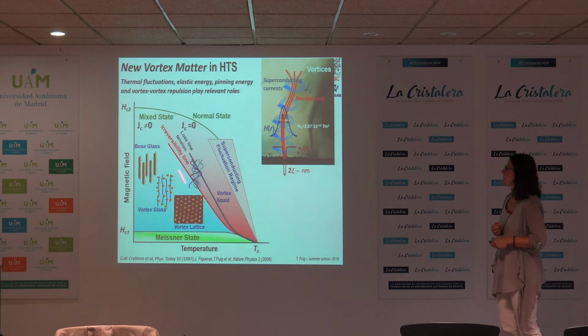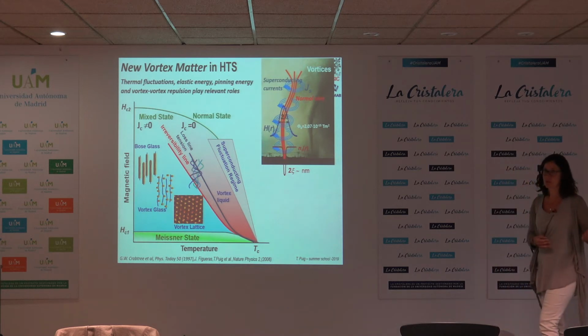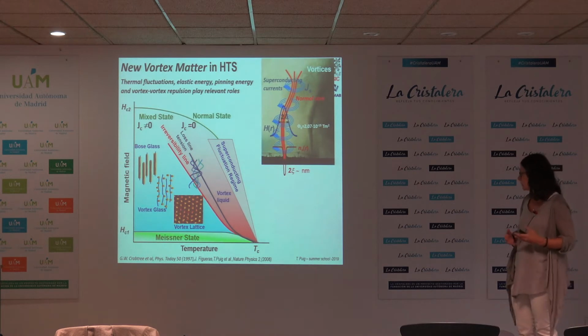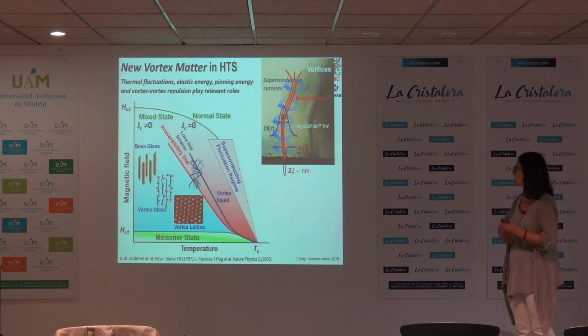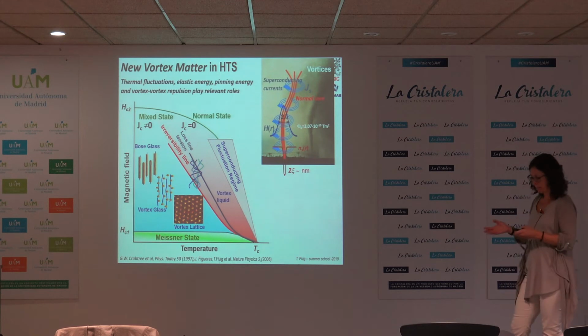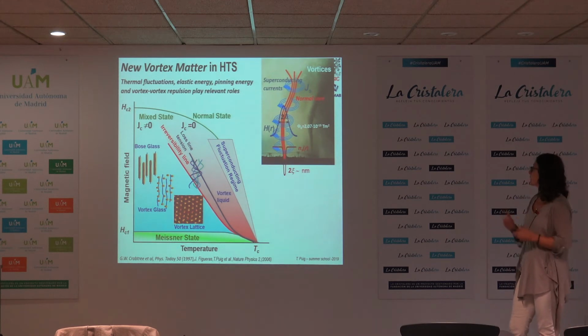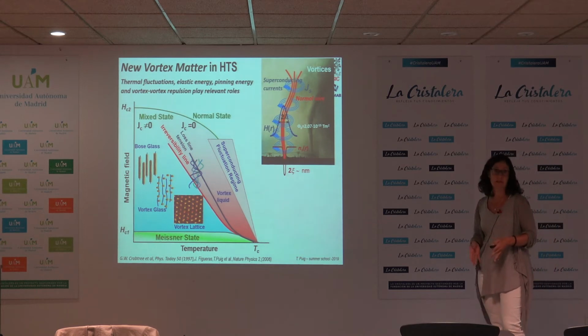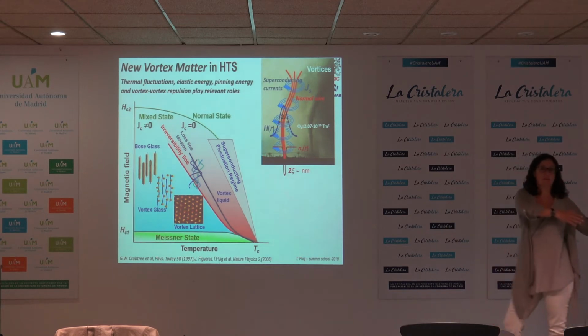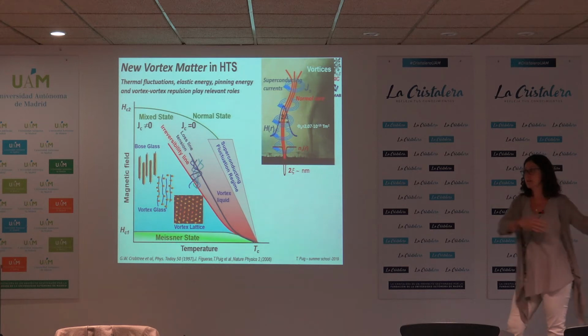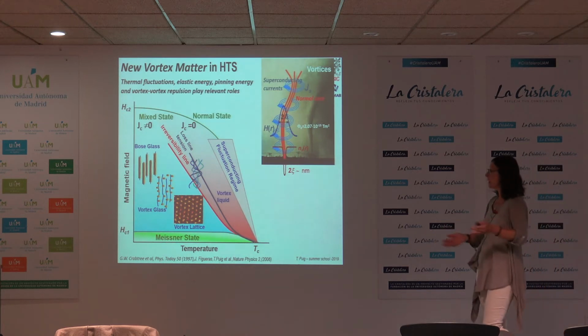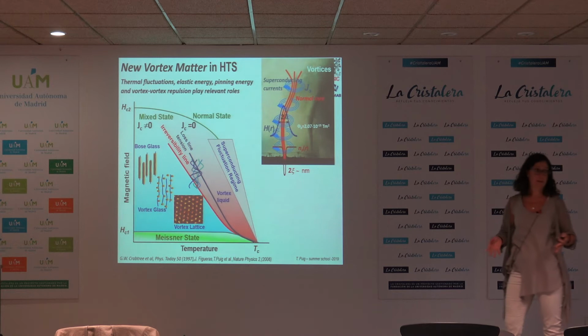But also, the interplay between defects and vortices is quite complex matter to study, and how each of the defects is affecting the pinning of vortices is important, because we are in very low coherence lengths, the defects of the order of a few nanometers are the ones which are pinning centers. In the case of niobium-3 tin, we had grain boundaries as pinning centers. Here, grain boundaries have to be avoided, and in fact, the pinning centers are nanometric defects.